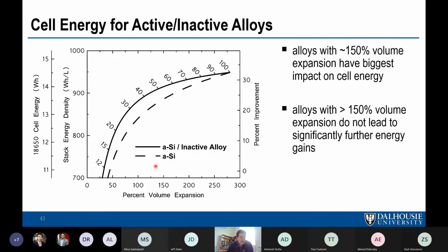And like we saw in the previous lecture, the volume expansion is perfectly linear. You know what the average voltage is, and so you can easily model all of these things. And so you can model what the energy density would be if you had pure silicon and we're limiting the potential to a volume expansion target, versus using an inactive alloy, where this is the energy density scale here, and you get a higher energy density at any volume expansion if you add an inactive component.